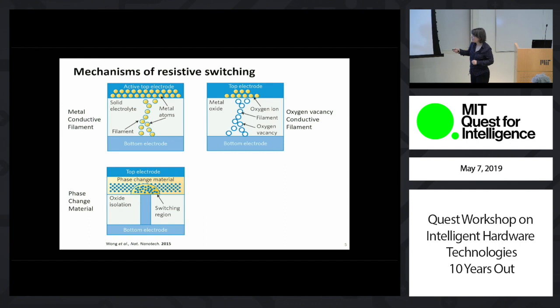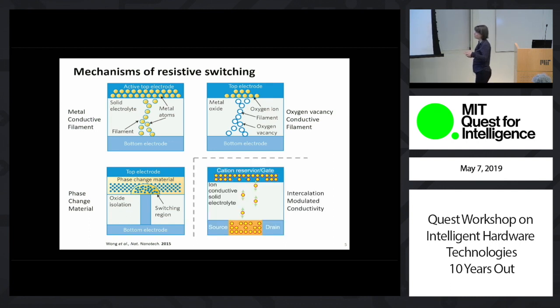And we also deal with phase change materials where Joule heating that we electrically supply gives rise to phase change that allows for metal insulating transitions. And these are most of the, let's say, conventionally studied mechanisms in literature. And more recently, we are also highly interested in a newer type of resistive switching mechanism, and that is based on electrochemical doping of cations into an oxide that changes its conductance upon such cation doping.